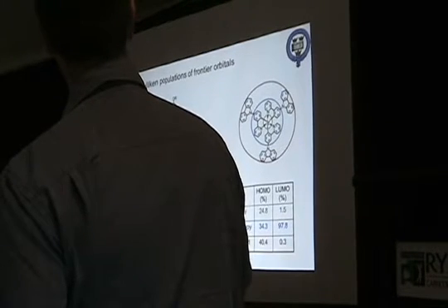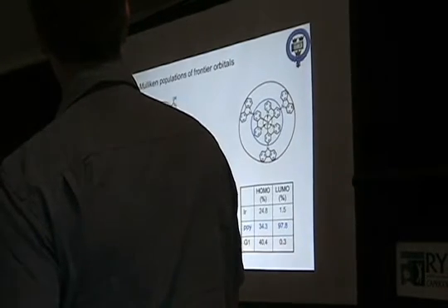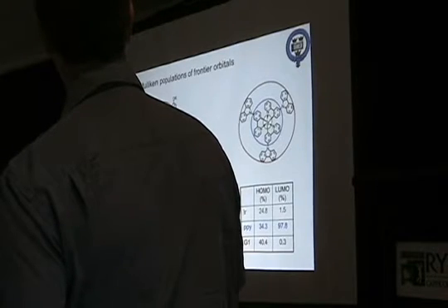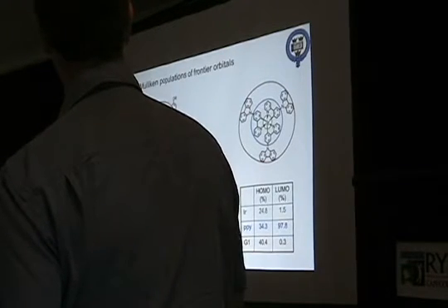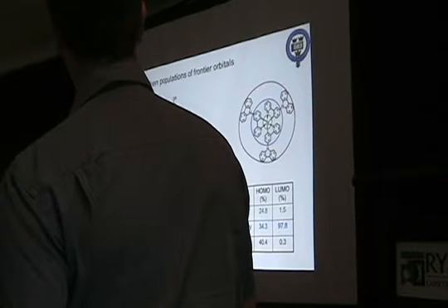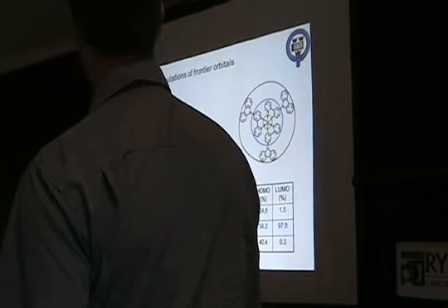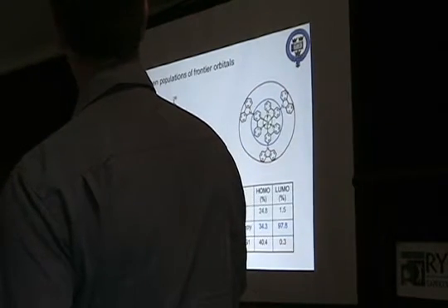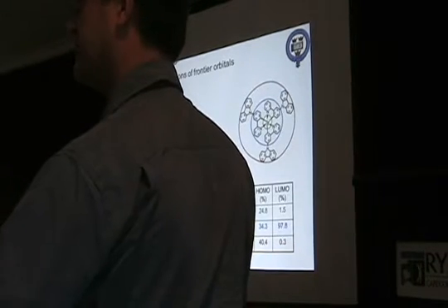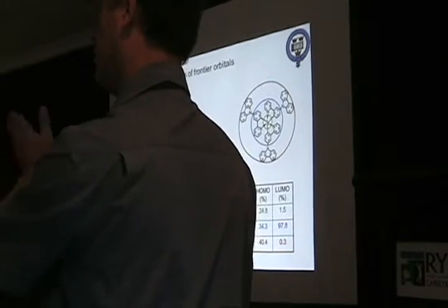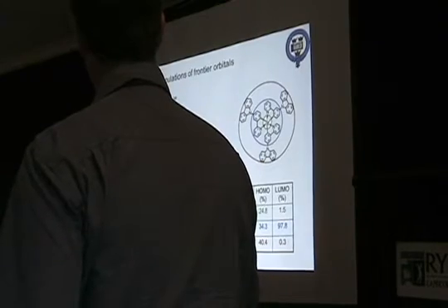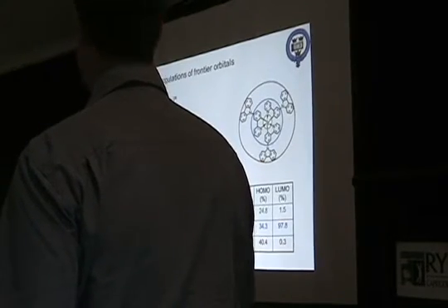Basically, in terms of the complex, which includes the iridium and the 2-phenylpyridyl ligands, you can see round about 94% of the orbital density sits on that central core, which fits with the hopping from core to core to core through the film. And there's only a very small percentage actually on the dendron.